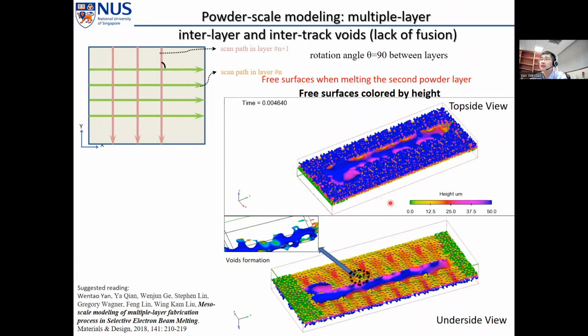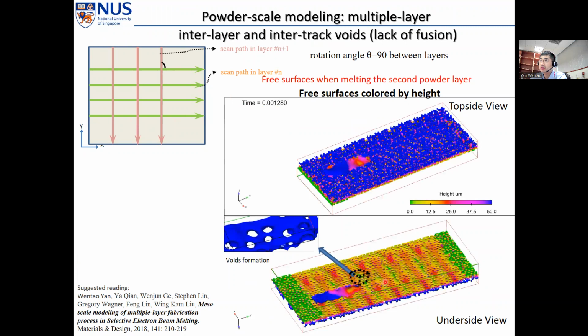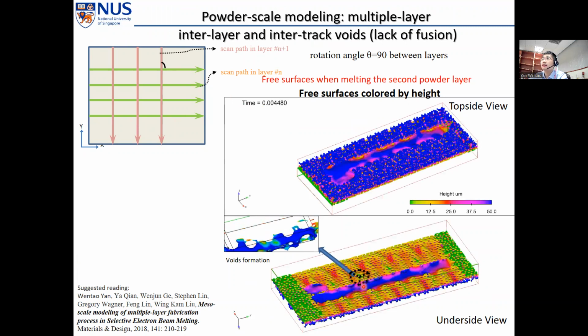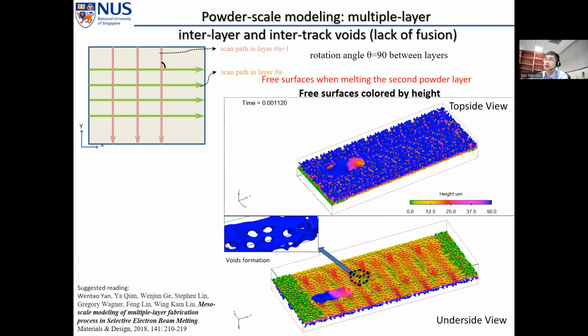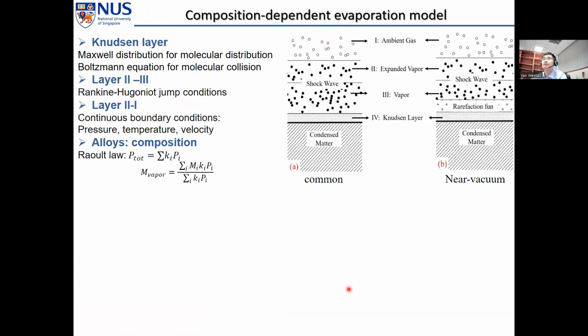And this is a free surface view. Here you can see the formation process of the lack of fusion voids. And actually the shape, size, and spatial distribution of the lack of fusion voids, they all agree well with our experiments.